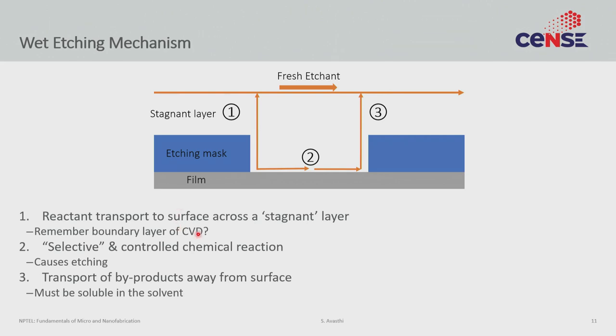The fresh etchant must make its way through this layer of byproducts in order to get to the surface. You always have this stagnant layer and something similar must happen when the byproducts leave the surface. If you have agitation or stirring, then the stagnant layer can be broken up a little bit and your etching rate can be a little higher. But even in those cases, there is always a microscopic layer of junk that you have to diffuse through before the fresh etchant can actually reach the surface.